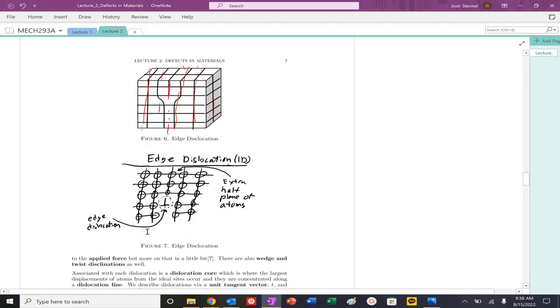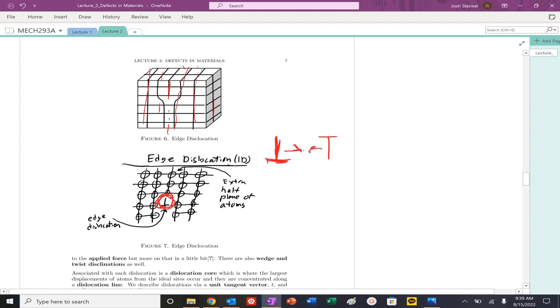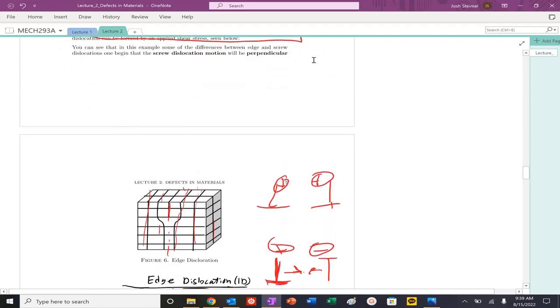This is your extra half plane. An edge dislocation is denoted by this symbol. It's important that this indicates where that extra half plane is. It's basically the polarity. Atoms or defects that are like this will actually attract, and we will see that in later lectures, because they want to complete this extra half plane. This is like a positive polarity, this is a negative polarity. But if I have defects that are this and this, positive and positive, these will actually repel. We can prove that in some lectures we'll see a little bit later on.